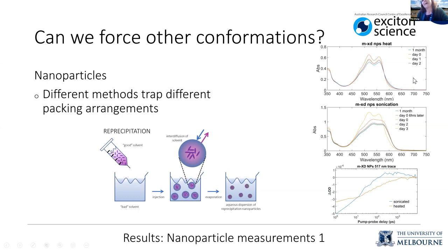So I can see that when I make these nanoparticles of dimers and I heat them, then I don't see that low energy J aggregate peak. But if I sonicate them, then after about 6 hours, they start to form the J aggregate peak. So there's some kind of rearrangement that's happening within the nanoparticle, and then that structure remains relatively stable over time.